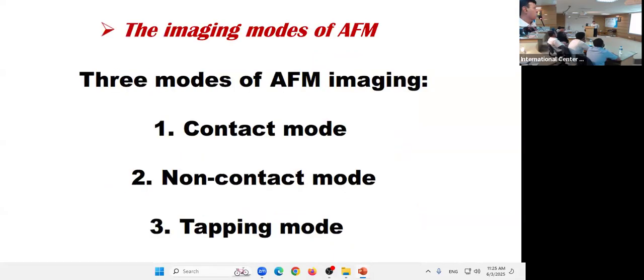There are actually three imaging modes. One is called contact mode. In the contact mode, the sample and the tip directly come in contact. In many cases we do not recommend this, but for certain materials like polymers or very small nanoparticles which are very much fixed to the surface, you can use it because the resolution of the image in the contact mode is much better than the non-contact mode.